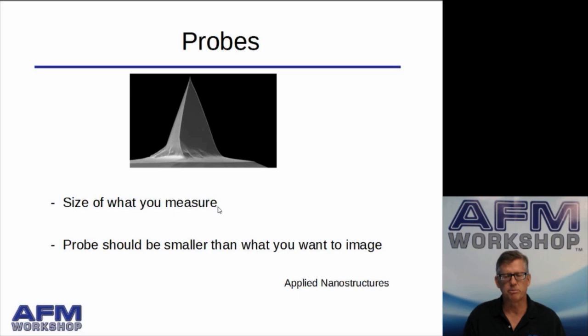Now, one of the things that's always important to remember is that with atomic force microscopes, we consider 10 to 20 nanometers low resolution. And for many other types of microscopes, like an SEM or TEM, that might be considered high resolution. So for 10 or 20 nanometer resolution images, it's not so important. But when you get down to nanometer resolution measurements, it's quite important. So the probe in general should be smaller than what you want to see in an image.